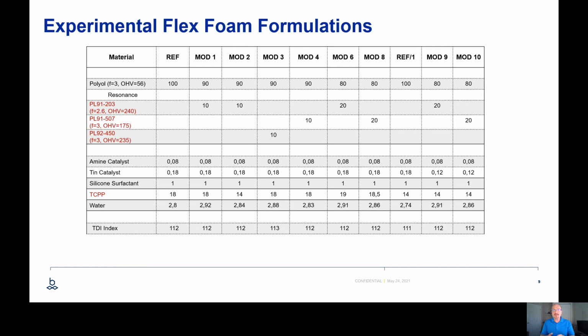And so for these particular systems, we just took a small amount of various of our aromatic polyether polyols. You can see PL91203, PL91507, PL92450 in small quantities, 10 parts out of 100 or 20 parts out of 100, drop them in to see what would happen with our materials. Would the mechanical properties be maintained? Would the reaction to fire actually be improved?